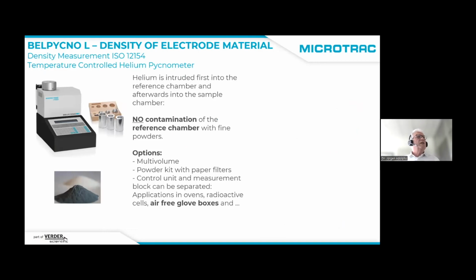Another interesting piece of information is the density of electrode material, for example, and this can be done with a pycnometer. You can place your powders into the pycnometer. In our systems, like the BELPYCNO L system, we work from the reference chamber by introducing about 2 bar of pressure, then releasing it to the sample chamber. From the pressure differences, we can then measure the amount of powder, and by the mass, we then know the density in gram per cubic centimeter, for example.